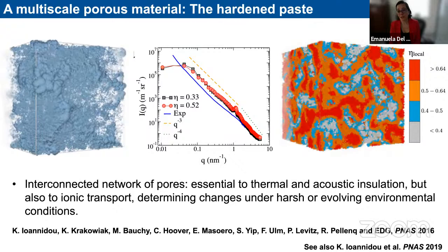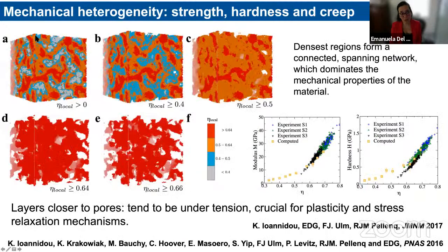You can use the same structure to compute the nanoindentation modulus as you would measure in nanoindentation experiments that my colleagues have performed. And you can see that our data do quite well, and that our data actually cover lower densities than what is typically measured in real materials. This is because the nanoindentation experiments are dominated by the toughest part of the material, which we can demonstrate by taking this structure and removing the external layer at the surface of the pores that have a slightly lower density.